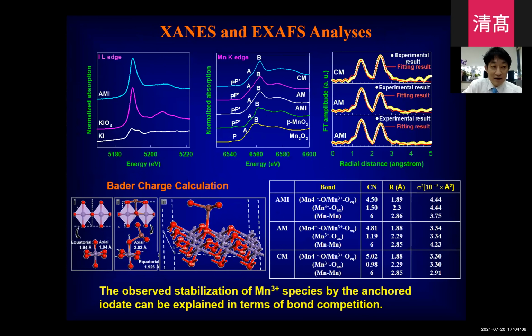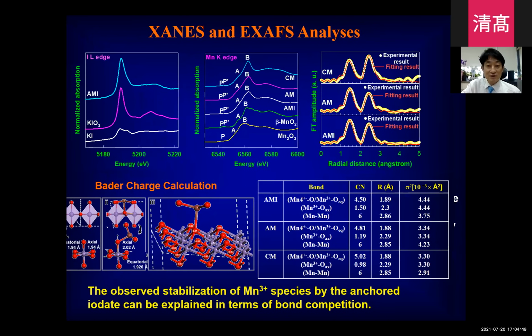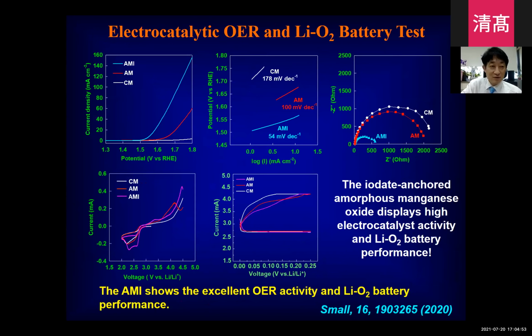From the iodine L1-edge spectra, as I told you in the very beginning, the pre-edge peak, the white line intensity is proportional to the density of unoccupied iodine 5p states. Like KIO3 pentavalent iodine, there are 6 5p holes. So the intensity is similar to the reference KIO3. So this is the evidence for the stabilization of the pentavalent iodine species. Also from the XAS analysis, we confirmed the stabilization of the Jahn-Teller active manganese 3+ oxygen octahedra. So the resulting material shows promising overall electrocatalytic activity and electrode performance for the lithium oxygen battery.